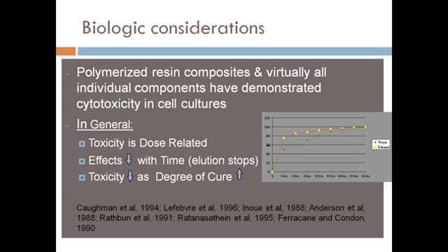What this graph is showing is the cumulative leachates from a composite in either water, which is the green line here, or ethanol, which is the red line right there. You can see that there's a burst release in the first 3 hours of whatever it is that you're releasing. It's worse with ethanol. But as the hours go by, up to 1 day, regardless of the solvent that you're using or the diet of the patient, it tapers off.